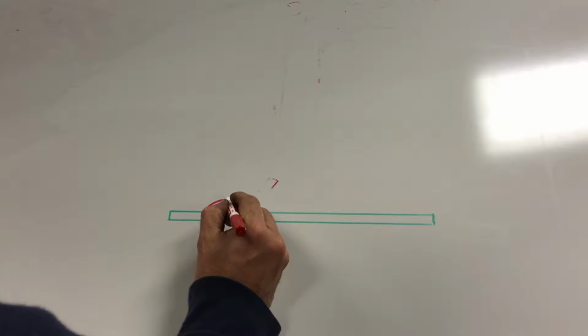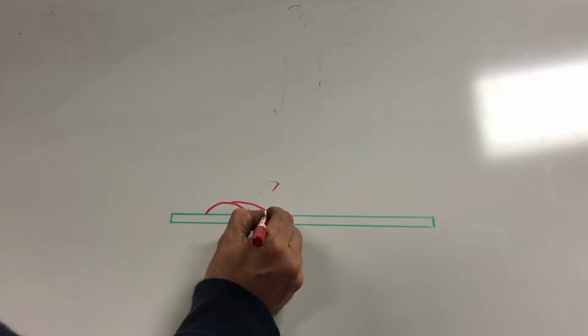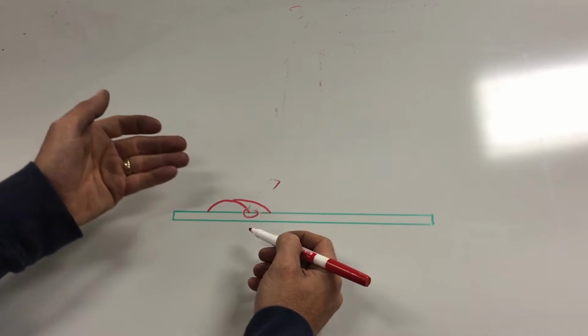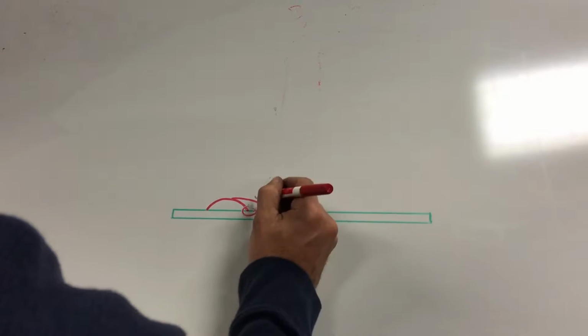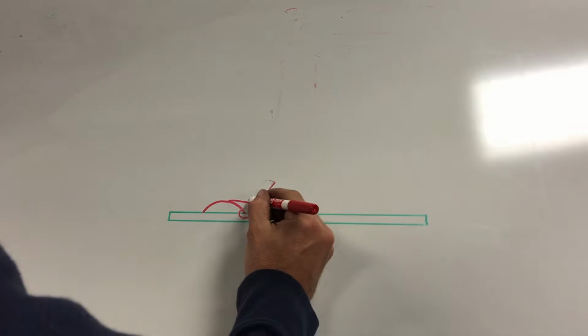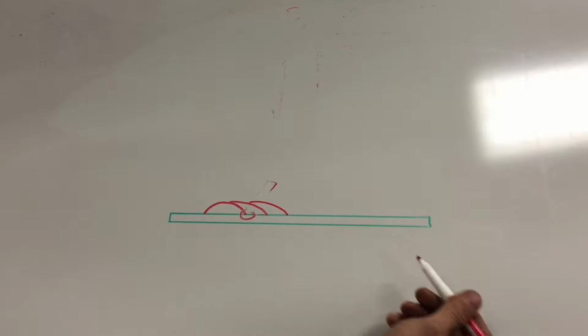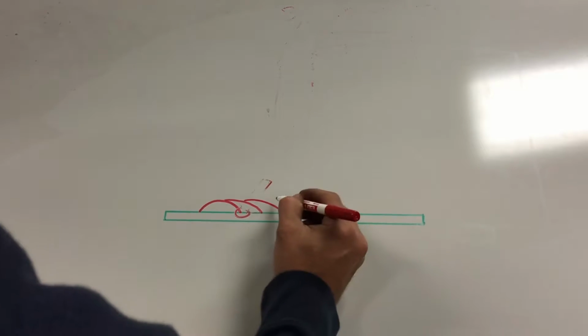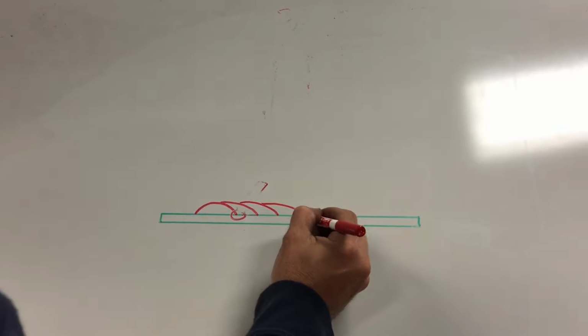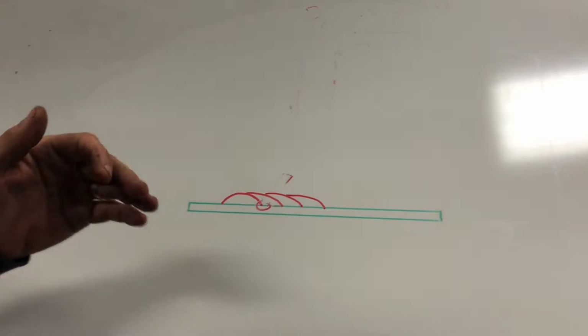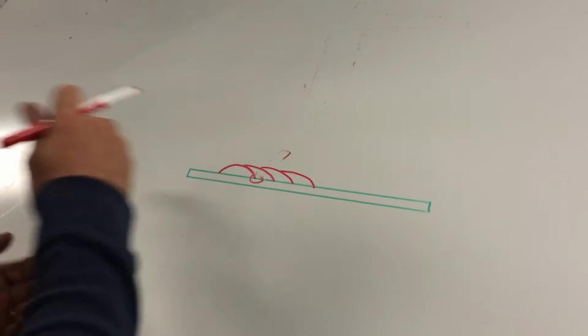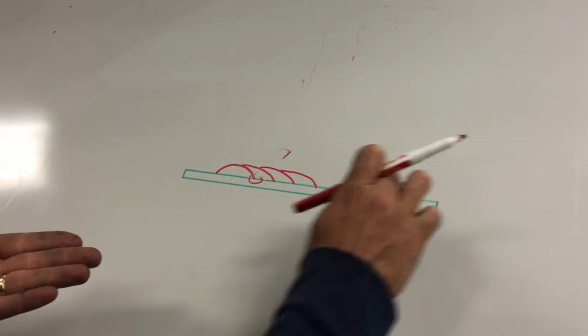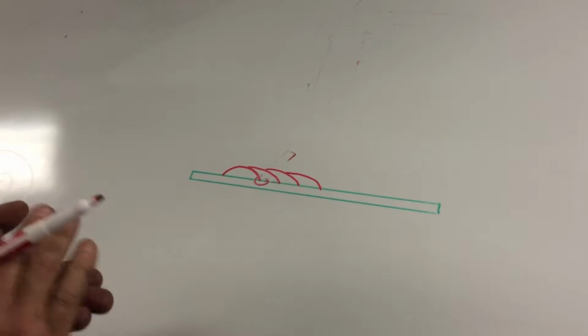We will come down the toe of that weld the whole time, and that should push the weld halfway up. We will clean this weld, then we'll repeat the process with the same angle, covering half the weld. Clean it, then we will repeat the process again. So when you're done, and this is cool, you should be able to take your hand across the top of these welds and they should be pretty smooth.